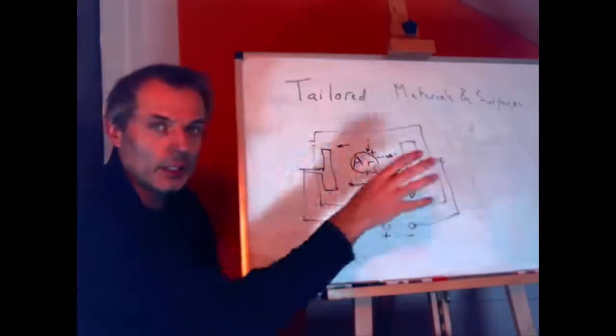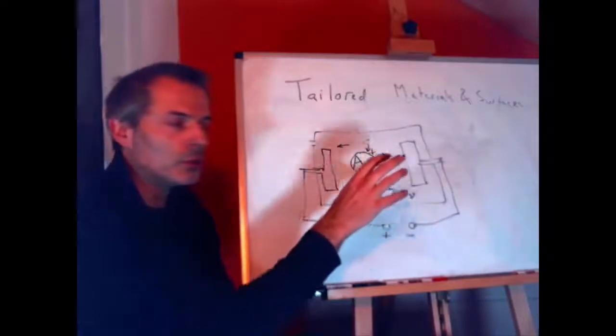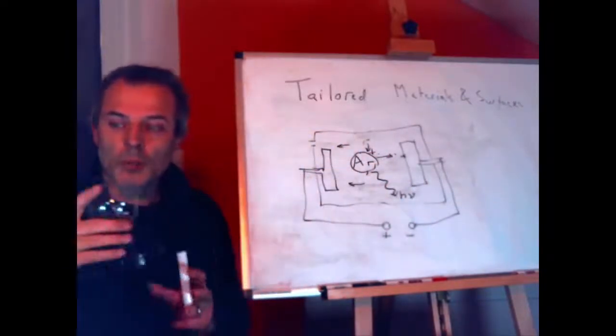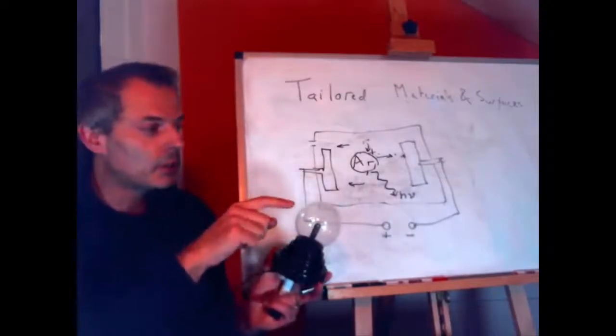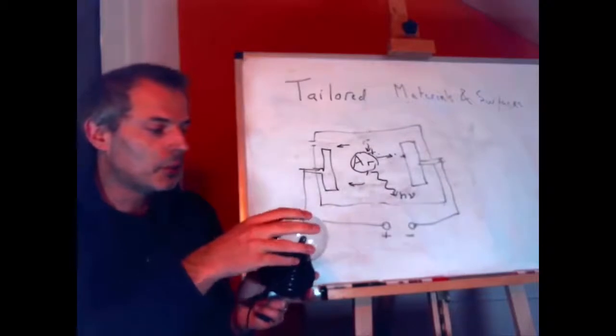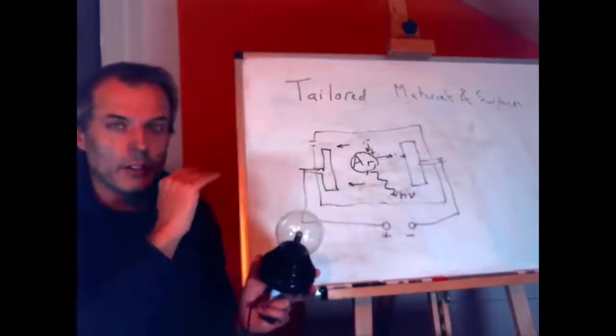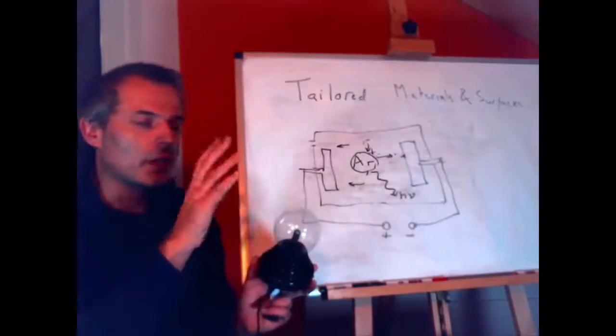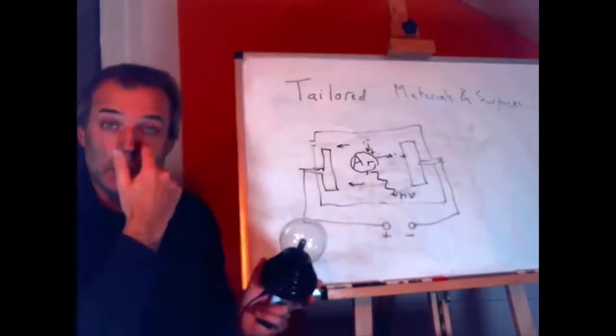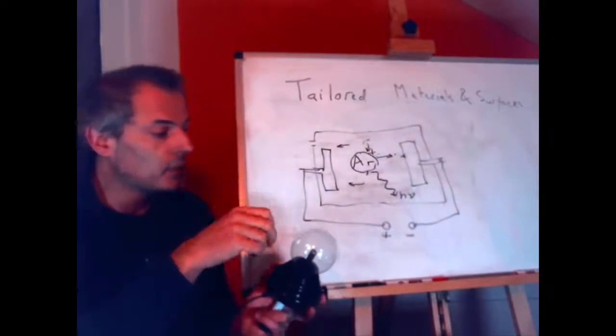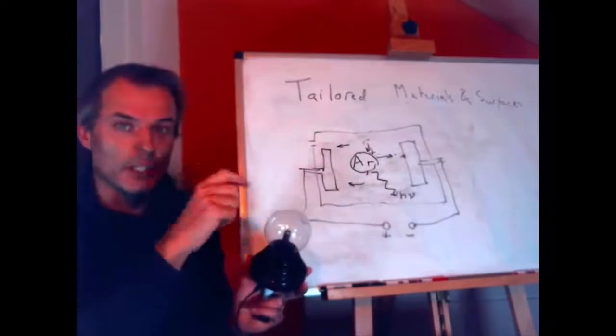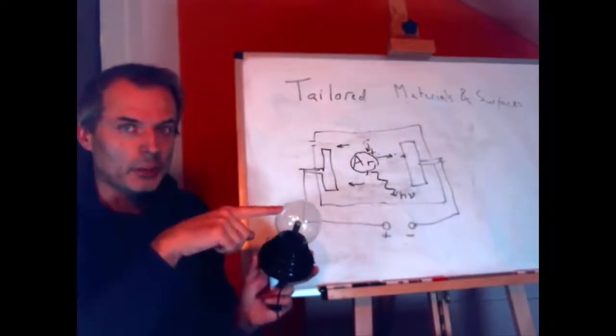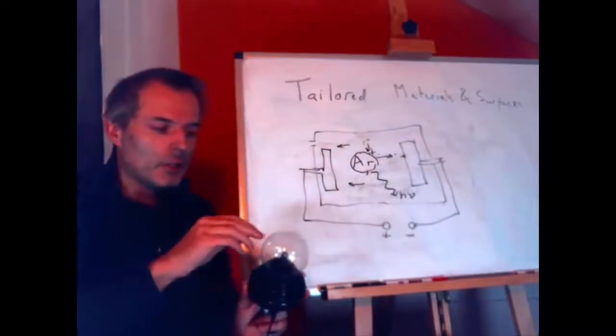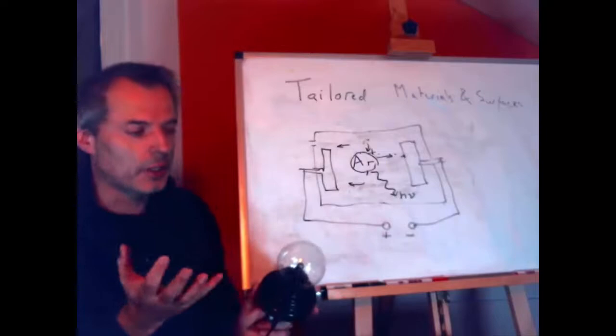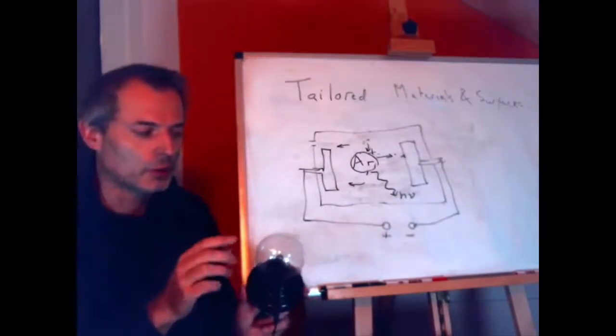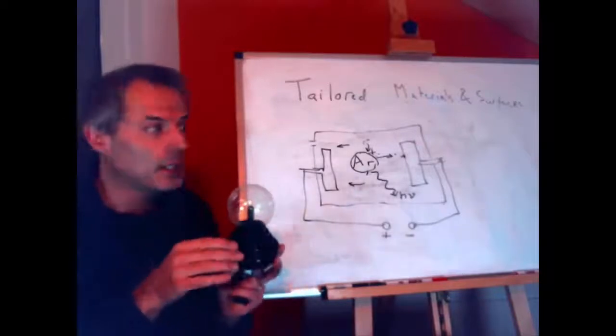So instead of going and whacking into the surface, they will move towards it and slow down, which is exactly what happens with my plasma ball here. It's a high frequency discharge, high enough frequency anyway, that the ions inside don't reach the ends, and so they just oscillate where they are. The electrons do escape, probably, because it's not that high frequency, but that allows the pathway to stay conductive, and that allows it to stay at the same position, because otherwise, if the ions dissipated, then there will be no reason for the arc to stay where it was. So that's why it stays pretty much where it is in this case.